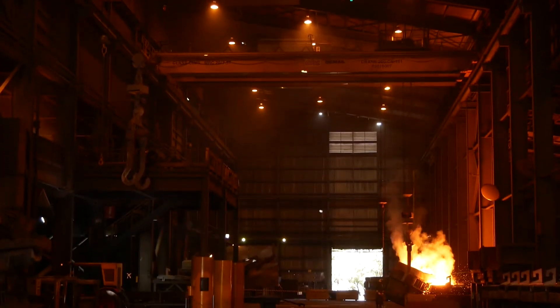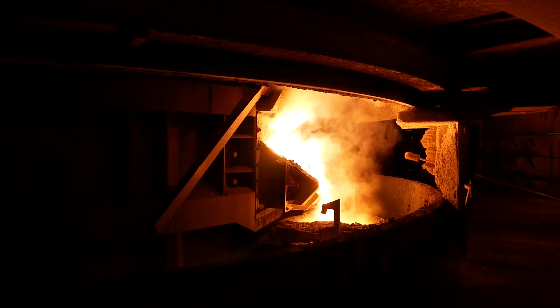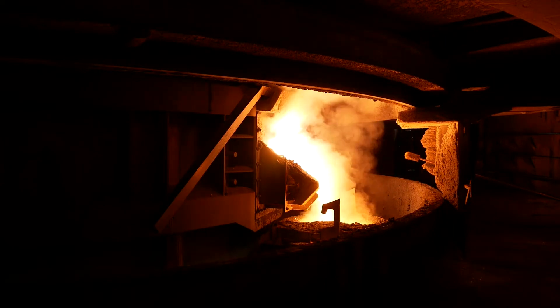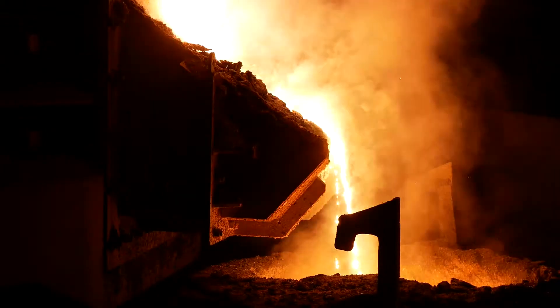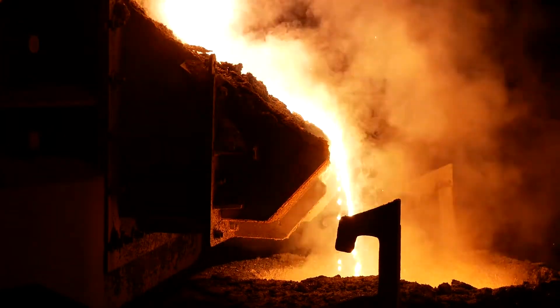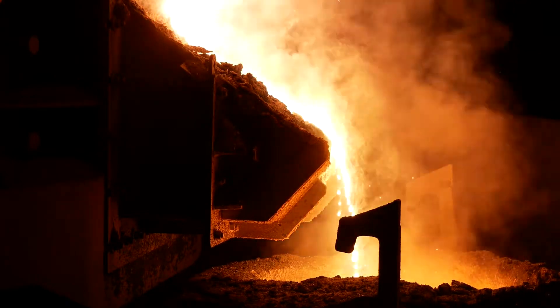The ambient temperature in the summertime, just in the furnace, it can get up to 60 degrees in there. The process itself is several thousand degrees, so obviously we need to put a lot of energy into this process because the bond between the oxygen and the silicon is extremely strong, and the only way that it can get broken is the input of a lot of energy.